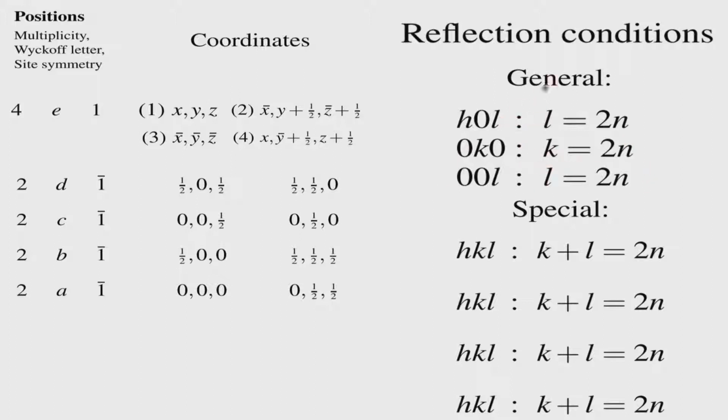When you get the systematic absences or presences indicated in the international tables like this, you have to make sure which is a consequence of the earlier listed systematic absence. The preference goes from HKL, where there are no conditions on general reflections, to HOL, the projection reflections, where there is a condition.